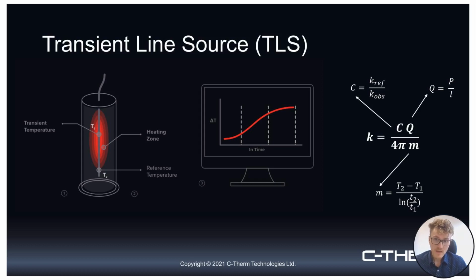To determine thermal conductivity, it's pretty easy. You have your K value, so your thermal conductivity, it's equal to a specific calibration factor, usually 1 near room temperature, multiplied by the heat that's applied, either power per length of your probe, divided by 4 pi and the slope of the line. So in the middle of the transient, there'll be a linear region, which you can typically find between around 2.3 to 4.6 log time. You'll notice a linear region, and that linear region is proportional to thermal conductivity. So increasing slope would mean a decreasing thermal conductivity, or a decreasing slope would mean an increasing thermal conductivity.